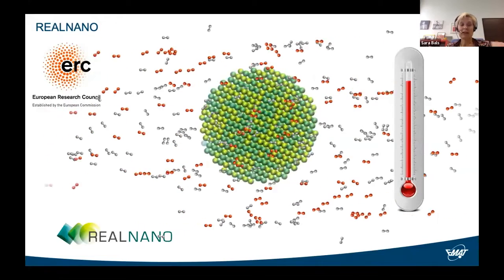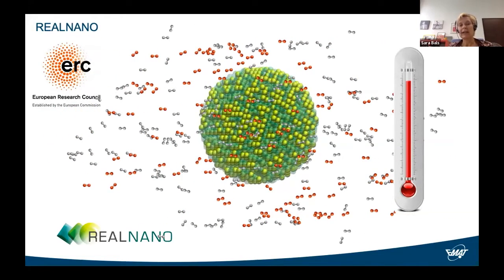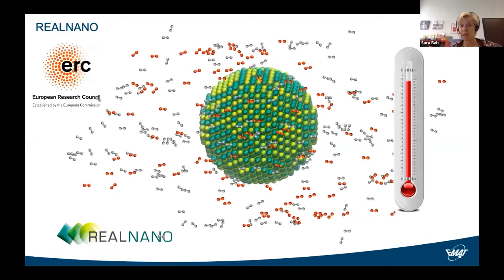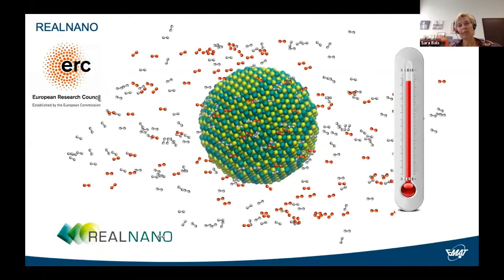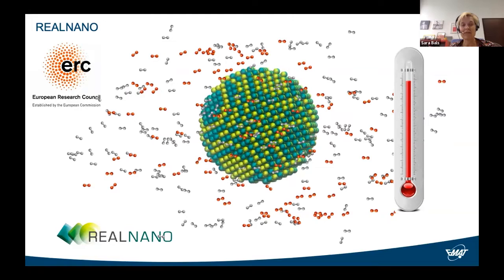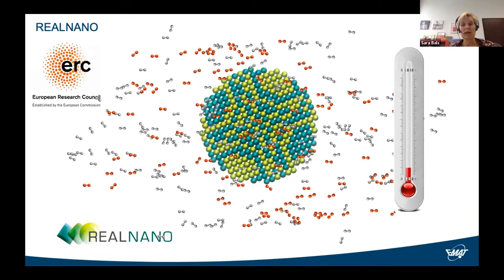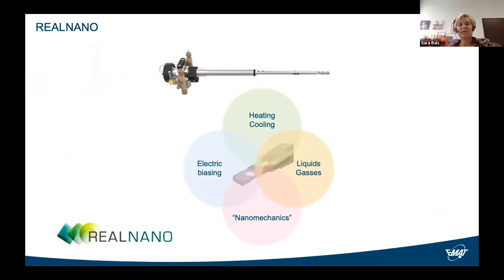In order to reach this goal, we need to combine in situ electron microscopy with electron tomography. Now, in situ electron microscopy can be performed using a dedicated environmental transmission electron microscope. But unfortunately, in Antwerp, we do not have such a microscope. What we do have is a very broad range of in situ electron microscopy holders. And using these holders, which are typically based on MEMS devices, we can perform heating and cooling experiments. We can apply bias or we can apply strain, and we can also create a specific environment such as a liquid or a gaseous environment.